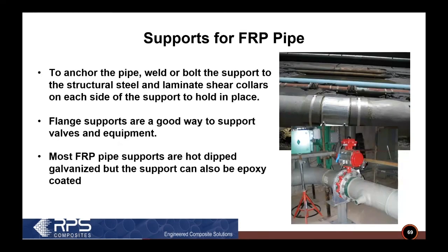If you want to anchor FRP, you can't just clamp down hard on the support. What you actually do is you make a support and you weld or bolt that support to the structural steel, and then you put a collar on either side of the support. It could be laminated in place or bonded in place. That's what you're seeing in the top picture. There are two collars bonded in place in this case, and that steel support is bolted down to the structure, and that's what anchors everything in place.